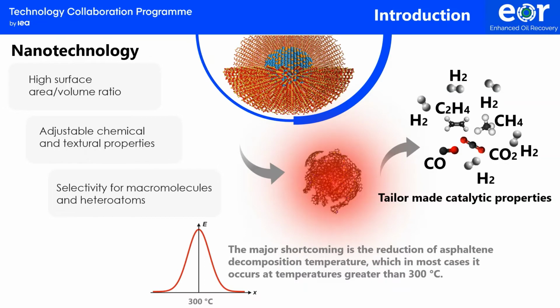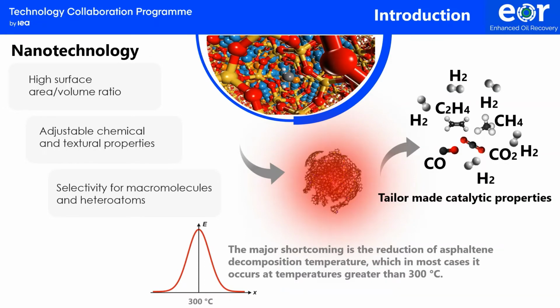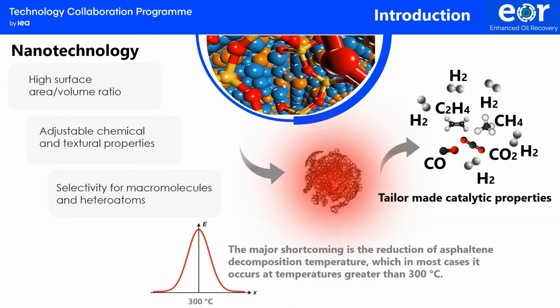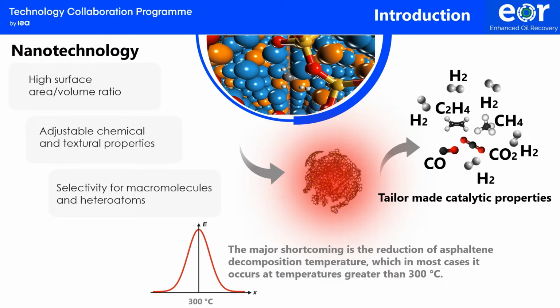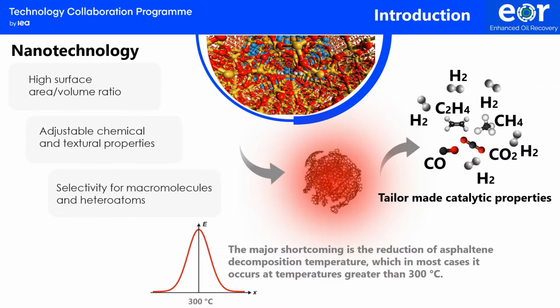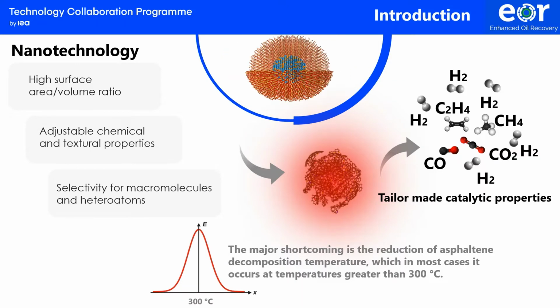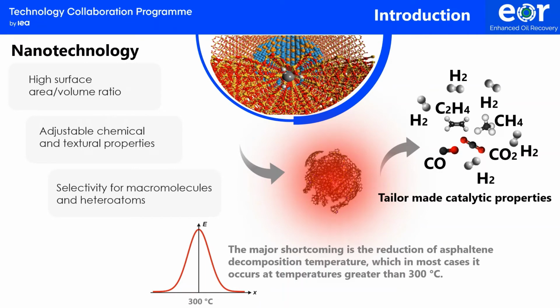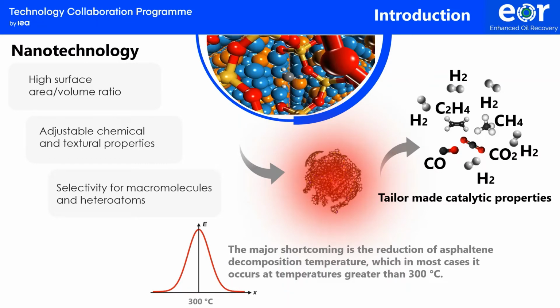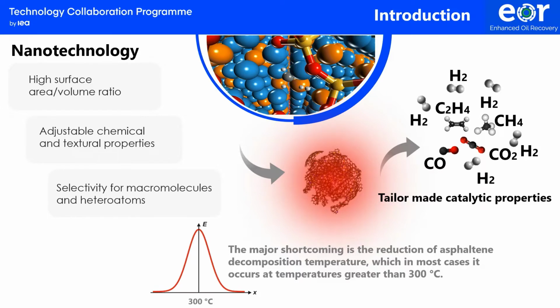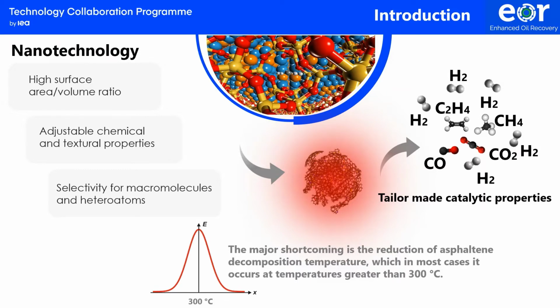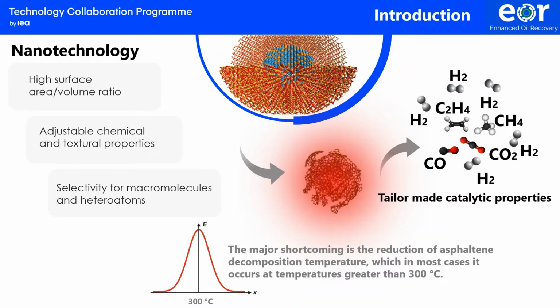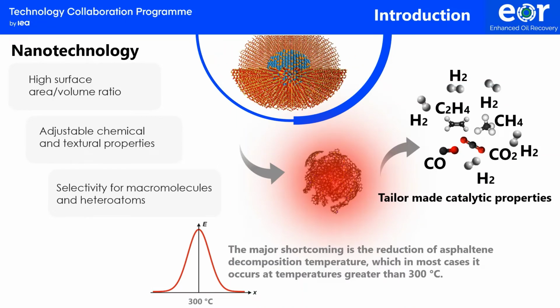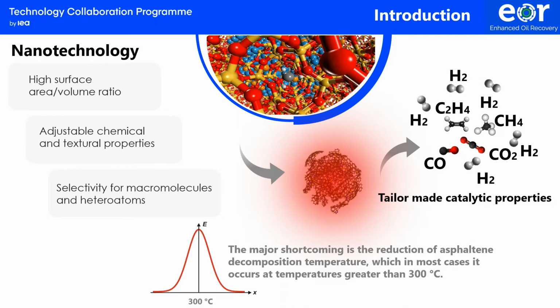The catalytic oxidation of asphaltenes using nanoparticles is an attractive idea. Nanoparticles present several properties and can considerably improve the potential of thermal methods to decompose asphaltenes and produce gases with added value. However, the synthesized materials tested were far from perfect, and the major shortcoming is the reduction of the asphaltene decomposition temperature, which in most cases occurs at temperatures greater than 300 degrees Celsius.